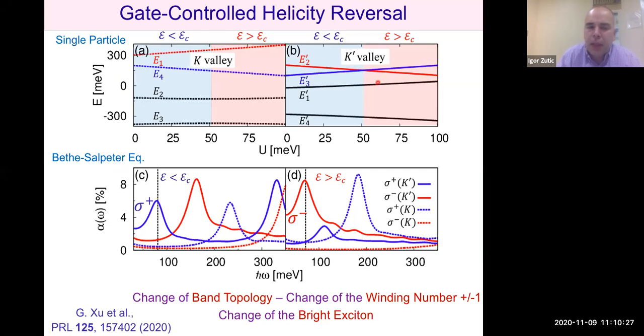And this single particle picture, which changes as a function of electric field and also may depend on this staggered potential, we can confirm by calculating the more rigorous Bethe-Salpeter equation. So here we have absorption spectra, and depending on the magnitude of the electric field, our low energy exciton can have positive or negative helicity.